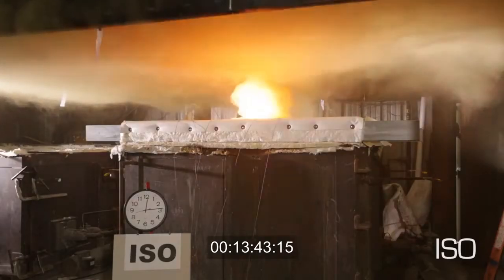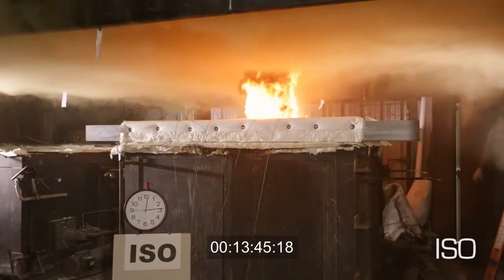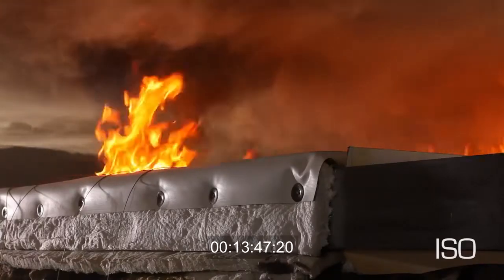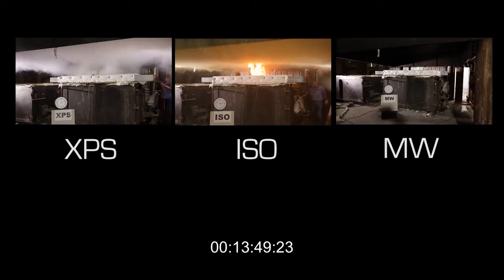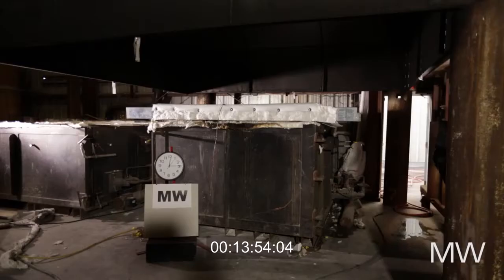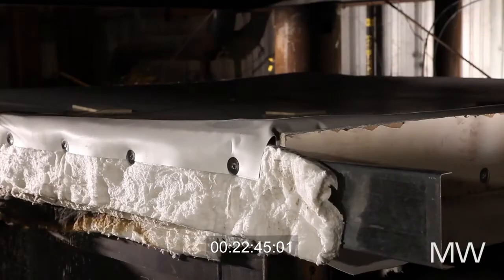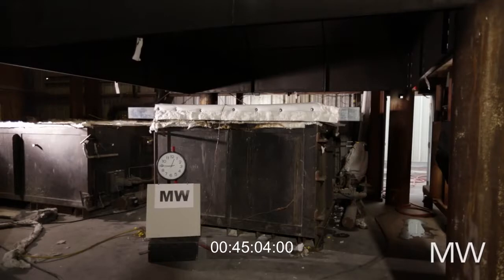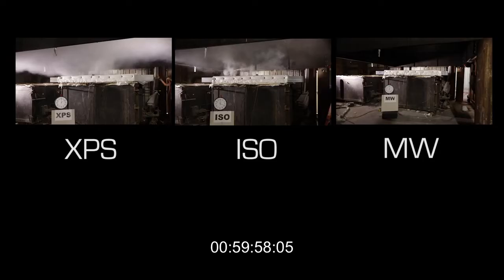Just under 13 minutes and 45 seconds into the test, the polyisocyanurate material ignites, and again we see a large quantity of smoke being emitted and a rapid growth in the fire. The mineral wool specimen at 22.5 minutes is still very stable. There is no smoke being emitted, and at 45 minutes we still see no indication of any deterioration in the material. At 1 hour the test is terminated as the mineral wool insulation is still intact.